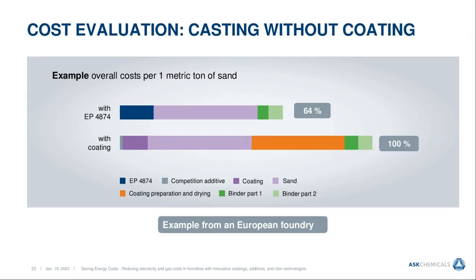What kind of cost savings could we achieve? If we consider the process with the coating, you have the cost for the coating itself, which is a dark pink bar, and you have in addition the coating preparation and the coating drying, which is the orange bar. So you need manpower for the preparation and you need energy for the drying. If we set this to 100%, and if we change to a coating-free process with implementing the additive EP4874, the blue bar, we can save more than 35% of your cost.